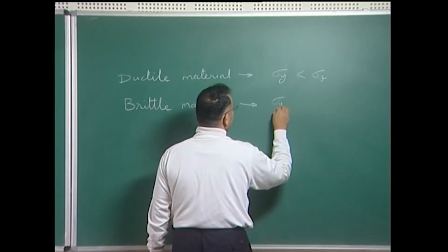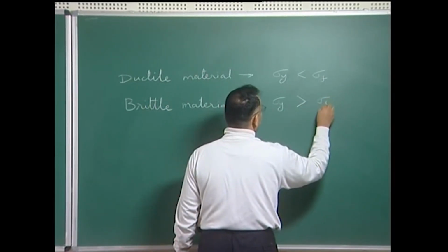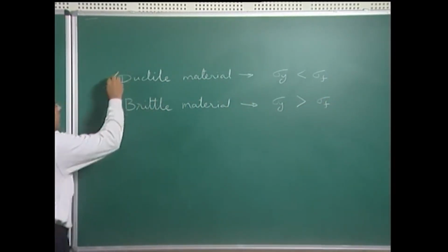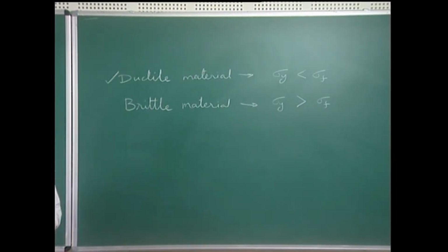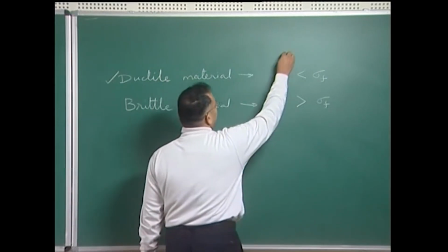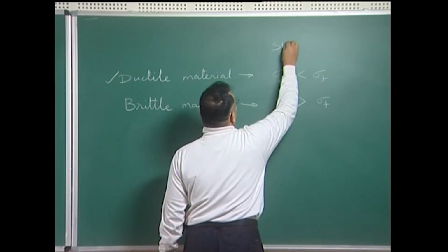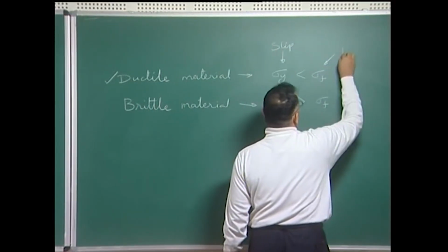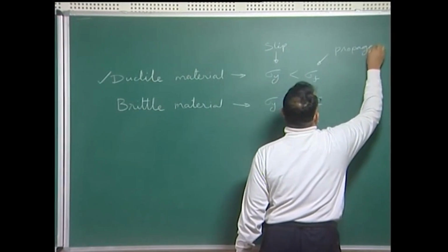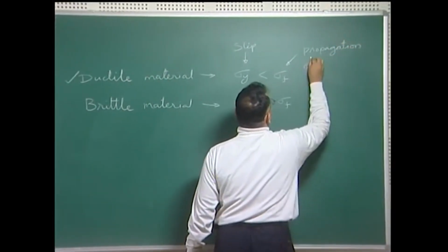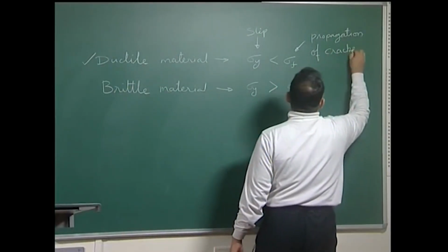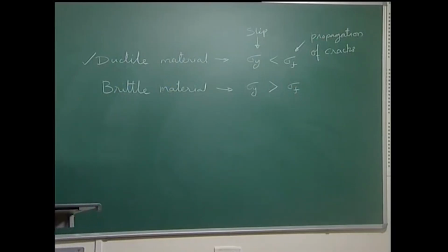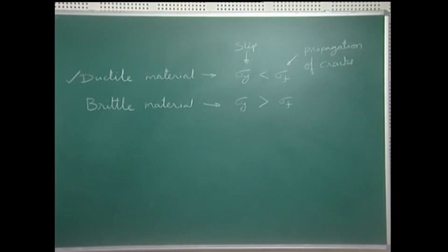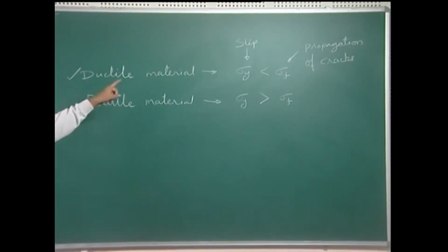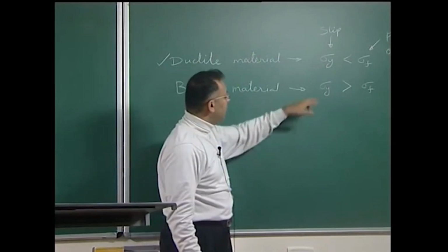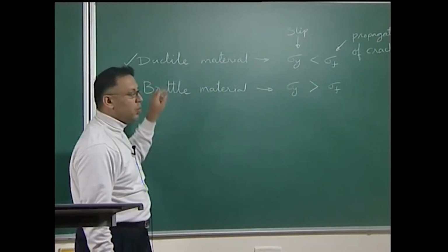a brittle material on the other hand is one whose yield stress is larger than the fracture stress. So, a ductile material will yield first before fracturing. In other words, the yielding we are talking about here is by a mechanism known as slip, and fracture is caused by propagation of cracks. So, when I have two competing mechanisms which can take up my external loading, one being slip, and the other being propagation of cracks, and if my yield stress is smaller than my fracture stress, then the material is called ductile.